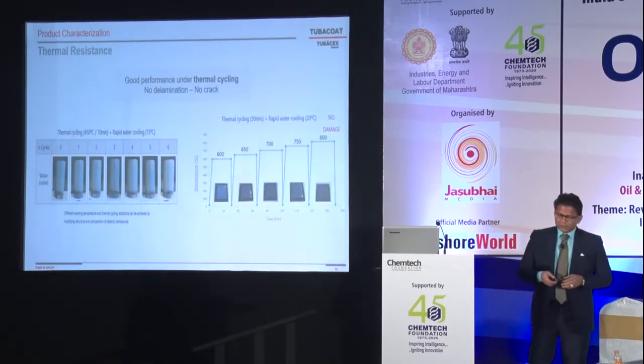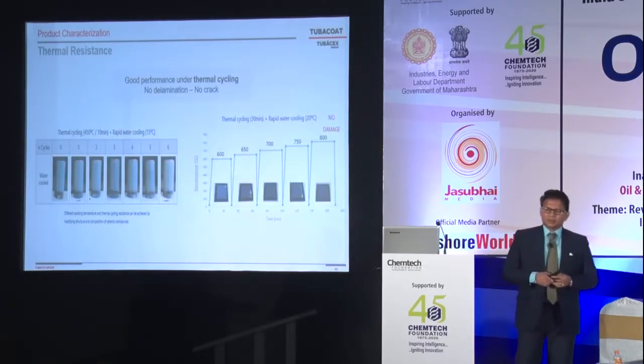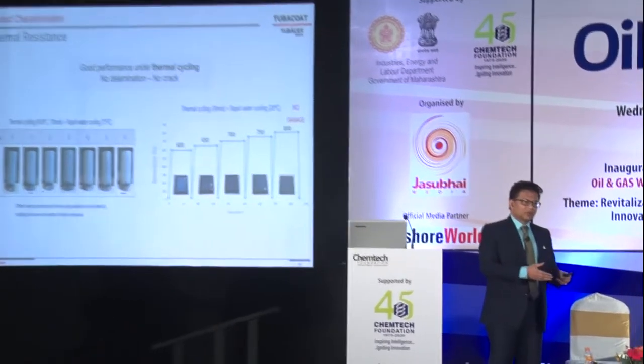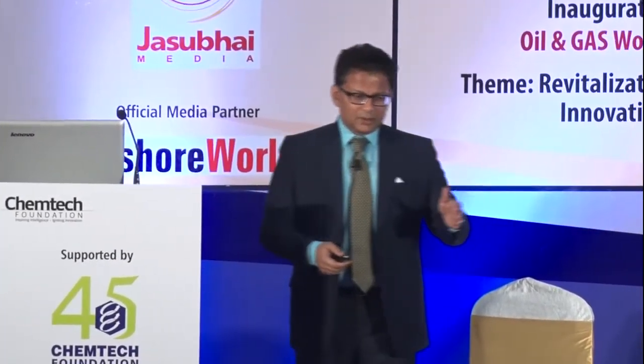So one of the key parameters in any refinery or chemical plant is the thermal resistance. You have a start of the unit, you have a shutdown of the unit, you have emergency shutdowns, so you have quite a few temperature variations. What I show in this slide is temperatures going from 0 degrees to 800 degrees, where you have rapid heating and rapid cooling. Absolutely, as you can see across the spectrum, the coating is intact. It works perfectly fine in the whole regime for any rapid heating and rapid cooling.